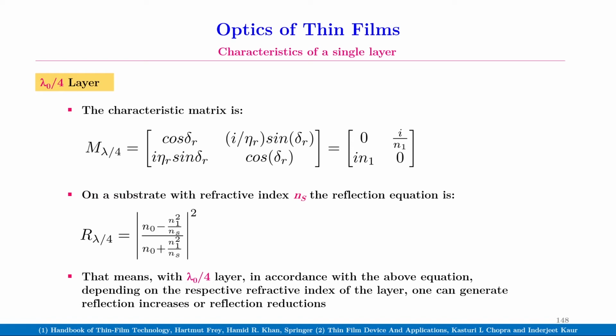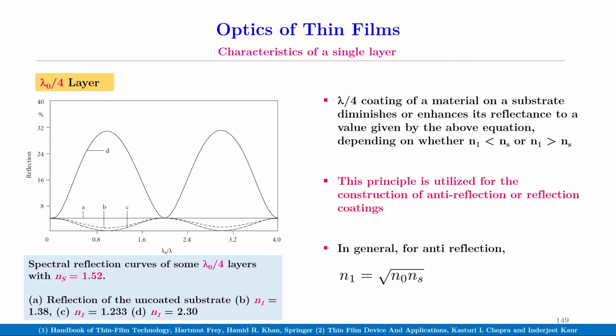That means with a λ0/4 layer, in accordance with the above equation, depending on the respective refractive index of the layer, one can generate reflection increases or reflection reductions. This figure shows the spectral reflection curves of some λ0/4 layers with substrate refractive index ns equal to 1.52. Curve A corresponds to the reflection of the uncoated substrate, and curve B corresponds to a thin film layer having refractive index n1 equal to 1.38, and curve C is that of a thin film having refractive index 1.233, and curve D is that of a film having refractive index n1 equal to 2.30.